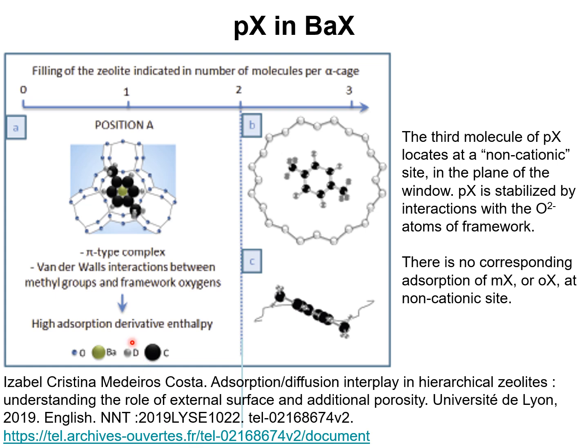In contrast to meta-xylene, the placement of the third molecule of para-xylene within BaX is not energy demanding because the longer para-xylene molecule can be located in the plane of the window and is stabilized by interactions with the oxygen atoms of the framework.